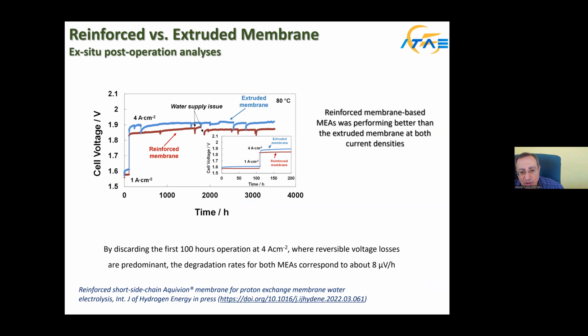Durability is also an important aspect, because usually to estimate it, since the degradation rate is very low, you need to operate your cells for about 4, 5, 6 months to really understand durability and make an estimation of the degradation rate. You can see that the reinforced membrane is characterized by better efficiency but also low degradation rate.